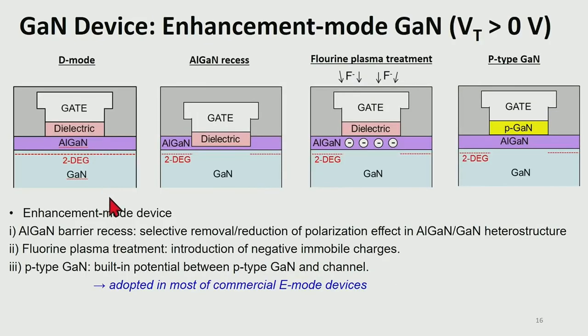So there has been extensive research to make stable enhancement mode GaN devices. Here we can review three different approaches. The first one is the AlGaN barrier recess. The origin of the 2DEG channel is the polarization field in the AlGaN barrier. So by removing the AlGaN barrier partially or completely under the gate, we can kill the 2DEG under the gate and make an enhancement mode device. This approach is the most straightforward, but there are a couple of process challenges. First, threshold voltage can be dependent on the remaining AlGaN barrier, but this control is not easy. It's a timed etch. And also during this etch process, the mobility under the gate can be degraded due to plasma damage.